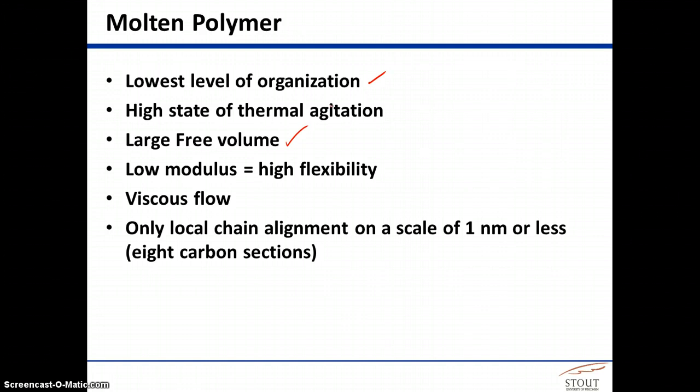In other words, the chains are moving so quickly that, due to those vibrations along the backbones of the chains, if we were to look at two polymer chains that are adjacent to each other and do a time average or something along those lines, we would see that there are these voids that would exist in between these individual polymer chains that we're going to be calling free volume, just because that motion between those two chains necessitates having some kind of an elbow room or some space in which those chains can move. Of course, that little drawing was exaggerated, but that's the idea, that there's that free volume in between.